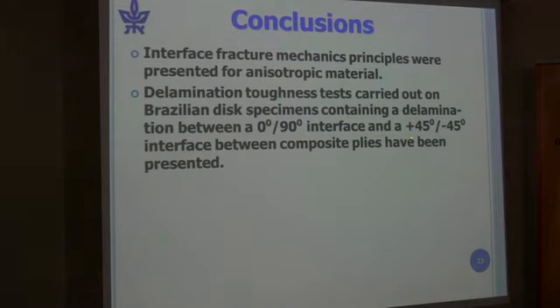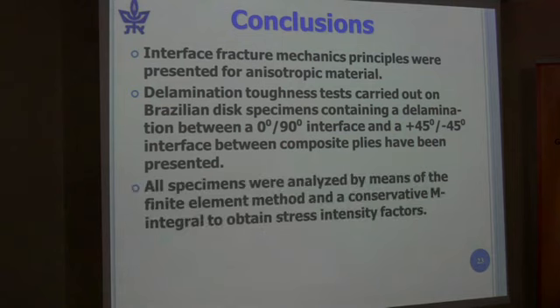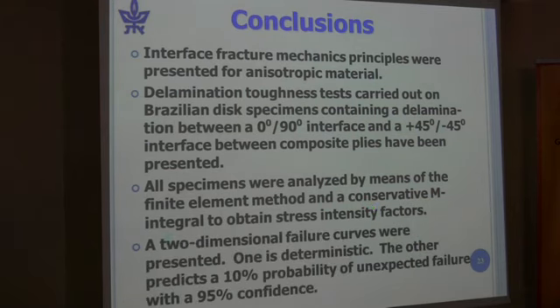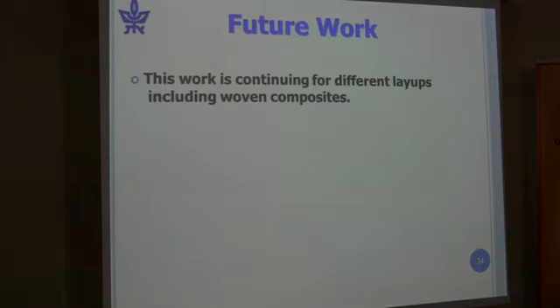We also did it for the plus 45, minus 45 degree interface, and this turns out to be a stronger interface. The G1C value is about 90 newtons per meter. All specimens were analyzed by means of the finite element method, which I didn't present to you, and conservative M integrals, which I also didn't present, I just mentioned them. And we obtained 2 failure curves. One is a deterministic failure curve, and the other one has a 10% probability of unexpected failure. We could do it with any percentage that a company, let's say an airplane company, would like, with a 95% confidence. And now we're working on different layups.